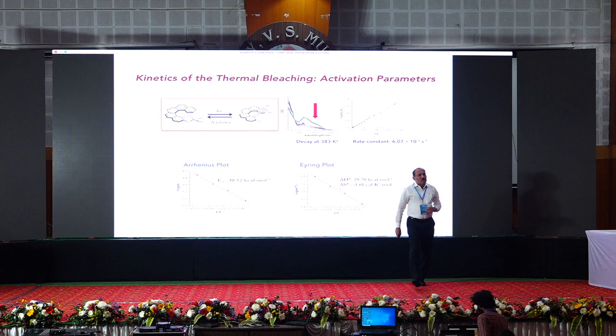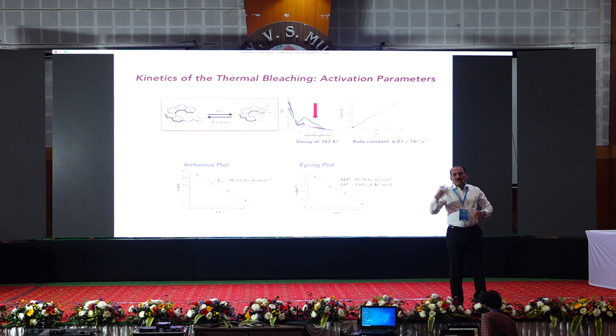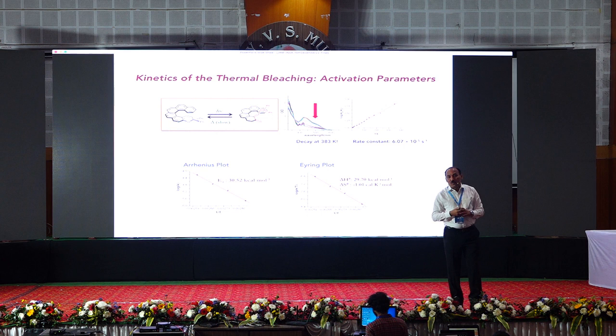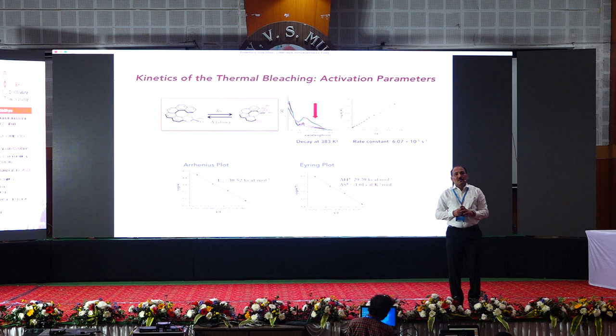In other words, you have here a system which with light becomes colored and comes back to colorless form when you heat it to about 110 degrees over a period of about 4 to 5 hours. Photochromic. It's clearly a switch. At room temperature, the colored form lives for about 53 years. It's truly a switch. What else can we do?